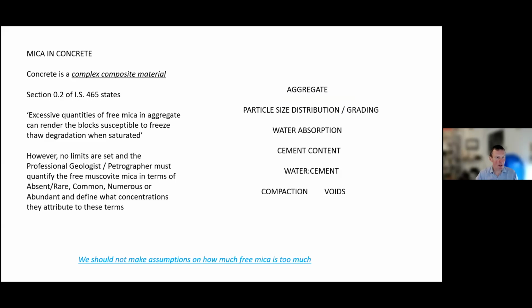Again, I will stress that concrete is a complex composite material, and there's more to concrete than just free mica. So we have to be very careful. IS 465 does not set a limit on the amount of free mica that's allowable, and asks the geologist to quantify in terms of absent, rare, common, numerous, and abundant, and define what they actually mean by these terms. We really have to be very careful that we should not make assumptions on how much free mica is too much. And unfortunately, there is a lot of focus on that, which is, I think, not always correct.